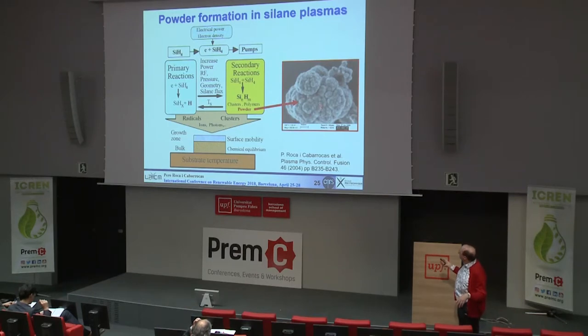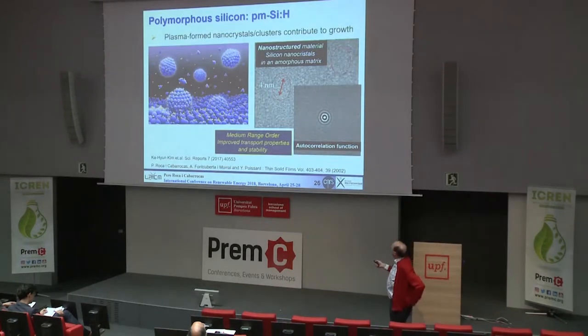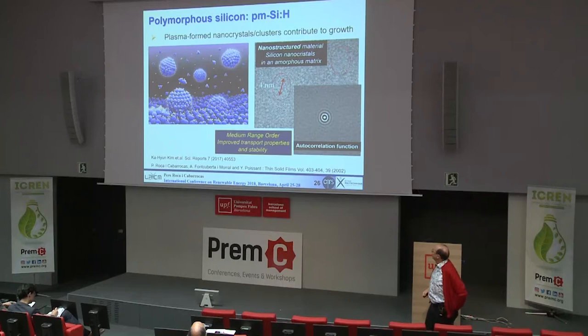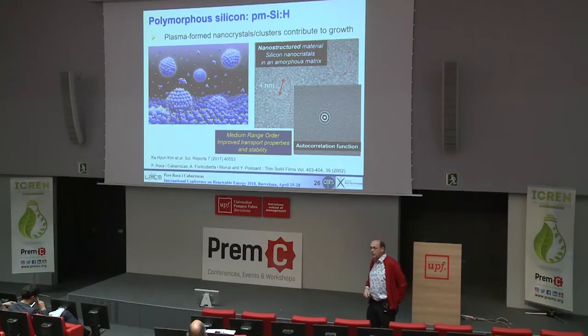And from this powder, which was a problem in 2004, I will show you that today this is the really big issue, because we can make perfect material using not the powder, but the clusters, the precursors of the powder. So those are the clusters, the precursors. If we have them incorporated in a thin film, we have this polymorphous material, which has medium range order and improved transport properties with respect to amorphous.